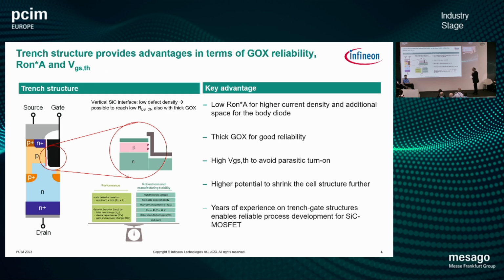with the trench MOSFET. What the trench MOSFET clearly brings as an advantage is, of course, a very low RDS(on) times A. We also see great reliability in terms of the gate oxide, which is critical for applications where you focus on reliability. And then we ensure a higher VTH, which avoids any parasitic turn-on. Another important point is that we see potential to further shrink the cell structure to gain more benefit with the next generation. The trench also builds on years of experience from the IGBT industry, transferred to silicon carbide, where we have enormous experience in this technology and gate structure.